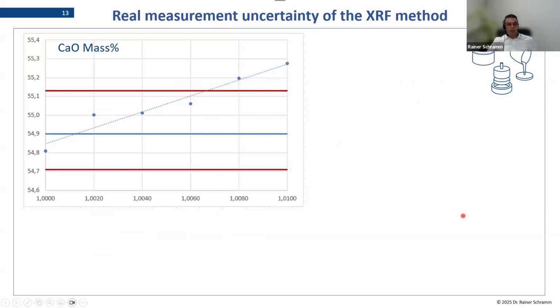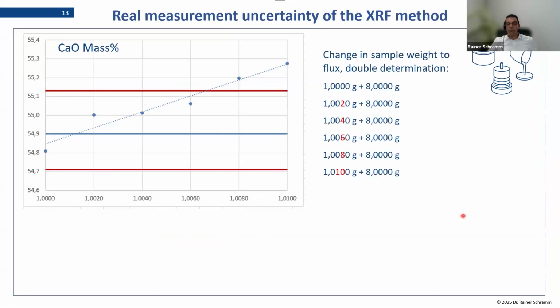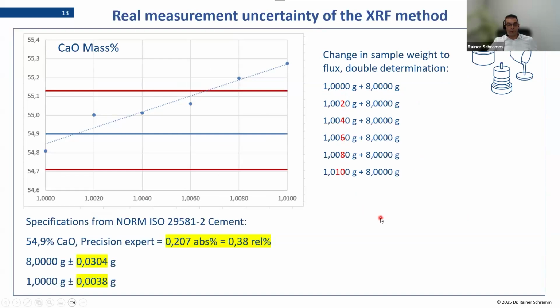Now let's see how this works in the real world. So what did I do? I weighed a sample exactly 1 gram and flux 8 gram. And now I really increased the weight for my sample to see how the result is affected. And what I also put in here is the blue line, which is the given value. So this is the certified value I should achieve. And the red lines, this is what the method tells me I should achieve as maximum error.